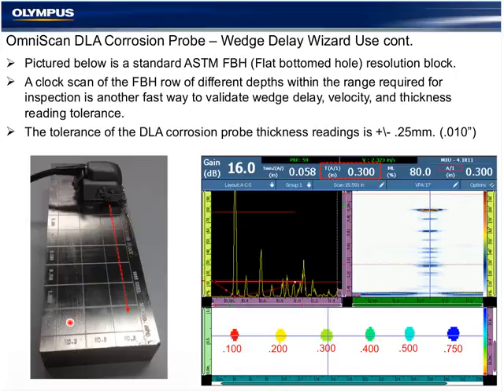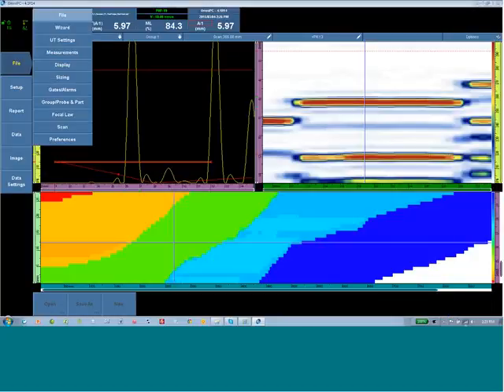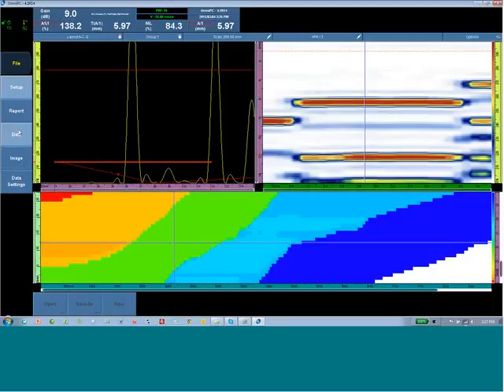If I set the probe on the edge of the block, clear the C-scan and hit start inspection and take either a clock or an encoded scan of the ASTM block, we'll see a similar way of inspecting or preparing for an inspection as the step wedge.